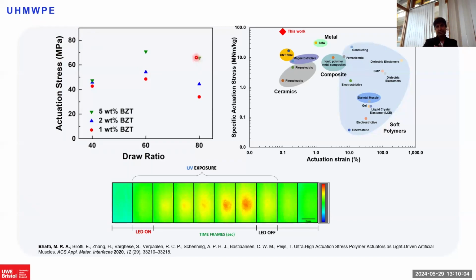And when we are reaching the maximum attainable draw ratio, although the Young's modulus is on the higher side, the negative coefficient of thermal expansion is on the lower side. So we are achieving a higher Young's modulus, but we are also getting a lower coefficient of thermal expansion, which we were thinking at that point is the base of getting actuation stress. But since these are counteracting each other, we thought that there should be an optimum value, which we observe at a draw ratio of 60.